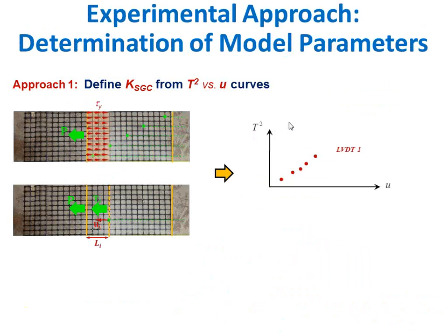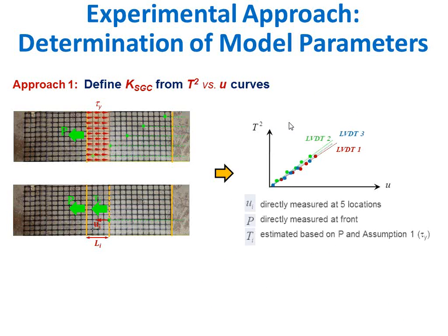It needs to be a straight line, and we'll know what the tension is if all this fits in place. Okay. So essentially, our current protocol is that we will measure the displacement at 5 locations within the reinforcement. We will measure P, the frontal load, not the load at each point.